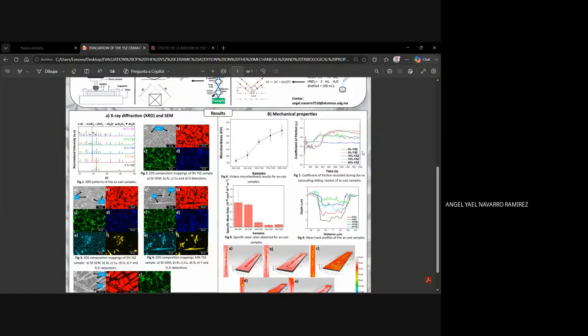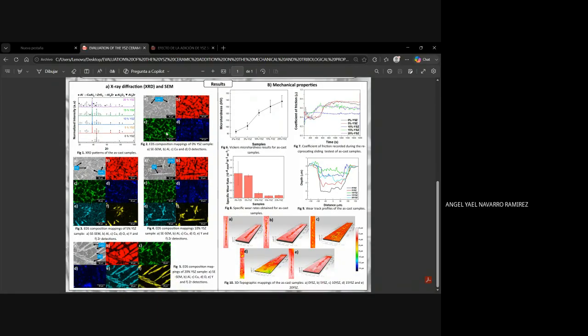Start with the X-ray diffraction. In figure 1 you can see the diffractograms and notice all the phases present in the material, starting with the first composition, 0% of YSZ, compared with figure 2, the EDS composition mapping of the 0% YSZ. You notice the first phases are pure aluminum and the intermetallic copper aluminum 2. This intermetallic is present in the microstructure, which is a dendrite. This is confirmed with the composition mapping, where copper is present mainly in these dendrites.